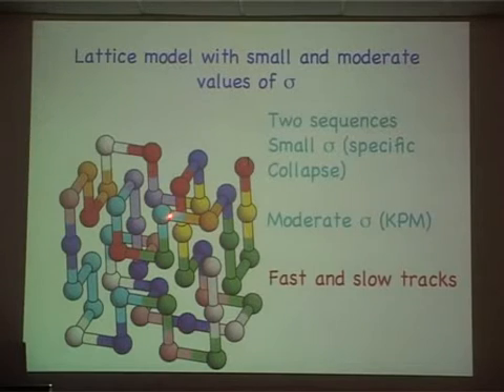We'll consider two sequences. One sequence has got this small value of sigma, which means the difference between the folding temperature and the collapse temperature, divided by the folding temperature, is small. The other one has a larger value of sigma, although they both have topologically the same ground state, but they have a slightly different value of sigma, and therefore they're a bit more frustrated, and they follow this kinetic partitioning that I described to you pictorially in terms of the energy landscape in the previous slide. Then we want to know what kind of collapse processes are present in both, and then with that I'll actually stop.